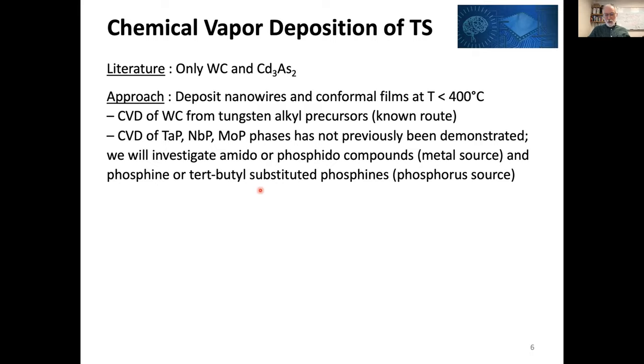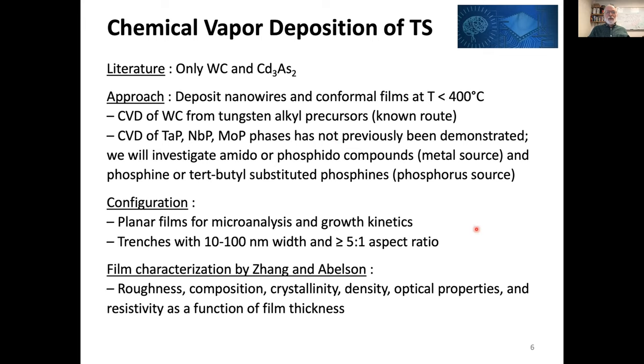I want to pause and say, I also have a long background in sputtering. Why is it we don't just do things by sputtering? One thing you'll appreciate is if you are sputtering elements that cannot become volatile, it's extremely difficult to hit a specific phase composition. Suppose we were trying to do a 3-2 compound. If we miss the stoichiometry, then the film has excess atoms trapped in it. So when we do CVD, we always try to design a route where excess atoms in the film form and leave in the gas phase on some byproduct species.